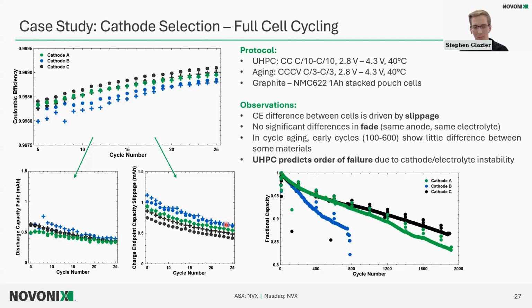So now we're getting more and more confidence that we've been able to rank these materials just within a couple weeks. And then after months of long-term cycle aging on multi-amp hour cells off our pilot line, we start to see these trends appear. Cathode B fails first within a couple months of cycling, and then 6 to 8 months later, we see cathode A and C start to split up.